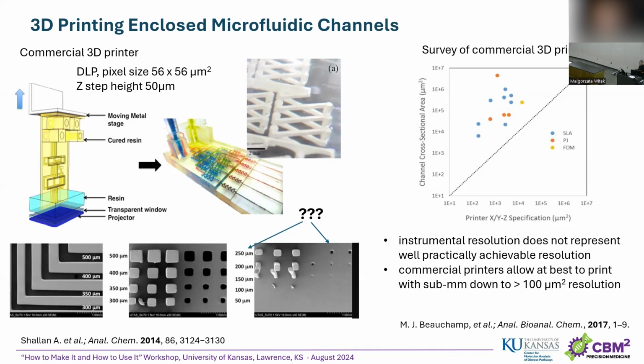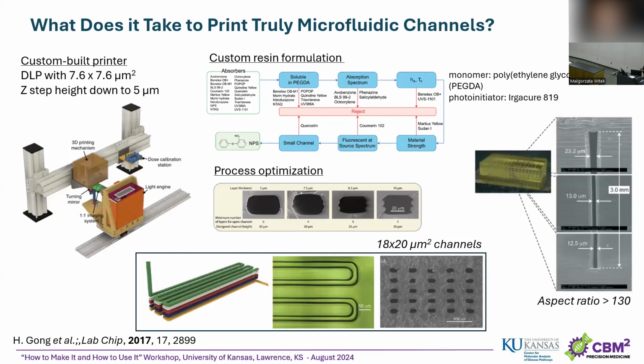And it all comes from the type of resin used, the viscosity of the resin, what the dose is, right? All these studies use the standard protocol. So they used those printers in the way, as I mentioned before, that you just make your design, come to the printer, press the button, and you get your part, right? So sometimes the difference was 1 order, sometimes 2 orders of magnitude, right? So what does it really take to do real microfluidic channels? Microfluidic channels that are below 100 microns, right? And the answer is it takes a lot of elbow grease.